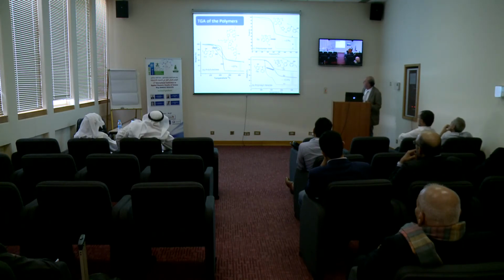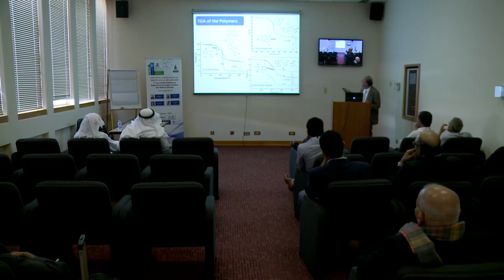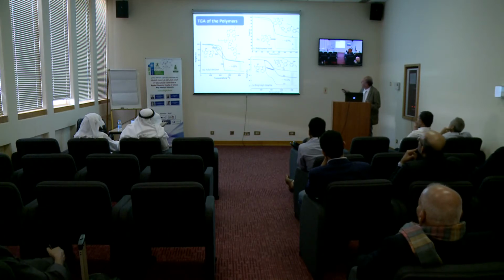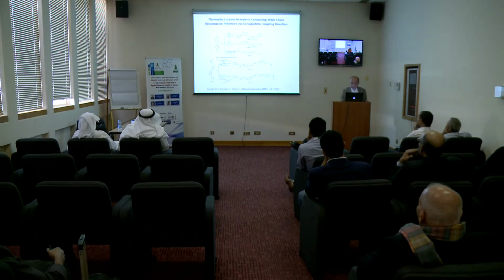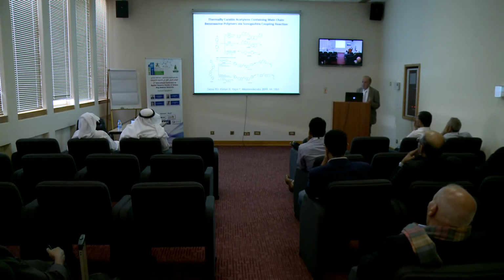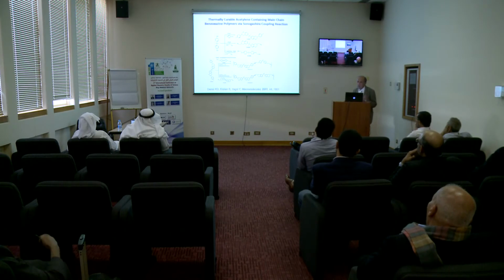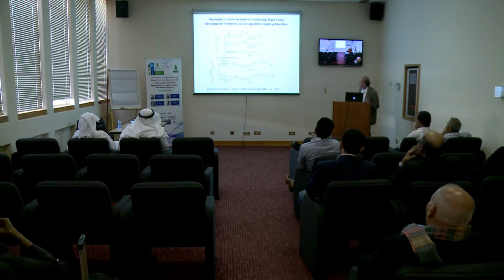Look at the polystyrene case. You see this is a linear polystyrene. This is cross-linked polystyrene, whereas this one is benzoxazine-attached polystyrene. You see the thermal stability, even after 500 degrees centigrade, they are still stable and the char yield is high. The same thing applies to PVC as well. So we did some other things. One can do even more coupling reactions.